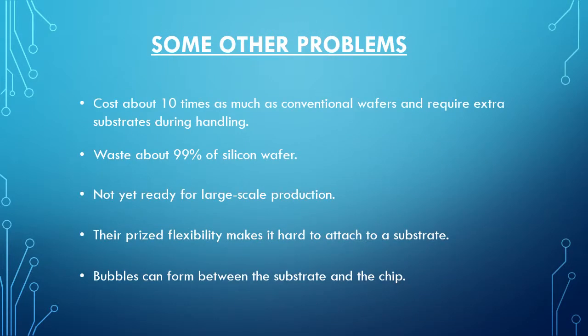Even if we manage to get an ultra-thin wafer without any damage, there are some other problems with the ultra-thin chips as well. First and foremost is the cost factor. They cost about 10 times as much as conventional wafers and require extra substrates during handling. On top of these, the technique wastes about 99% of the silicon wafer, as only the top layer is utilized for chips and the rest of the base is ground and diced away. Even though the chip film process makes chips as thin as 10 micrometers, it's not yet ready for large-scale production.